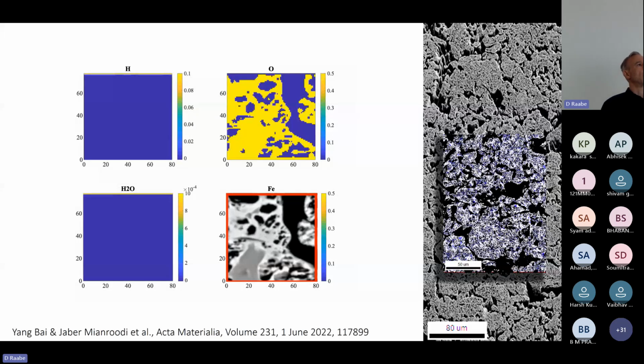And we use here, or bring together, two variants of this theory. One is the so-called Cahn-Hilliard model, which is a diffusive phase field model where you conserve the quantities. That means the diffusing chemical species are conserved, and you must describe the corresponding energy landscape between the wüstite and the alpha iron by a generalized Landau energy potential form that you can fit from Thermo-Calc data.